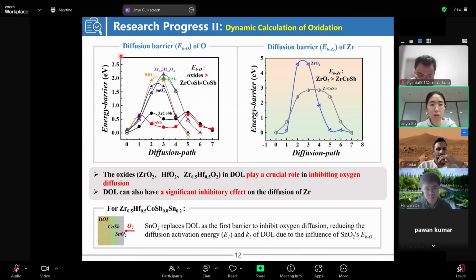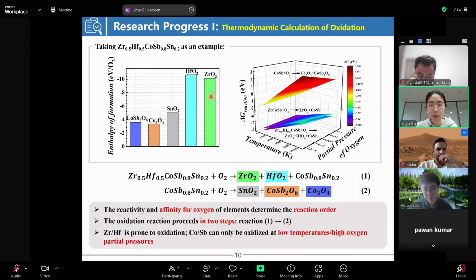I think the diffusion energy barrier is a key factor, because the Gibbs free energy is used to explain the thermodynamic reason for the DOLs. For the phases in the DOL, there is cobalt antimony and the zirconia or hafnia's coexistence. So I use the Gibbs free energy to explain why the cobalt antimony will remain unoxidized and coexist with the